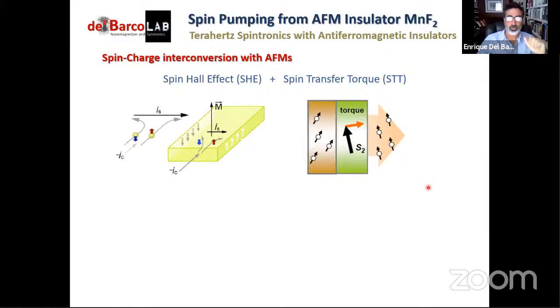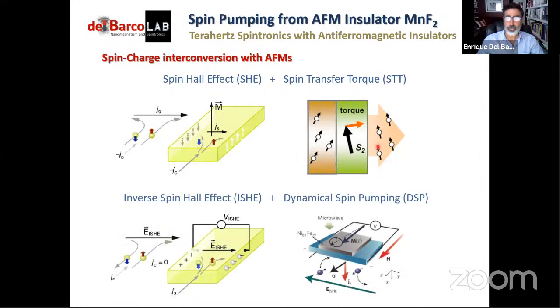All right, so I'm just portraying two of the most common tools that people in spintronics use to control the magnetic state of the system. It's the combination of the spin Hall effect, which converts charge current into spin current, and the spin transfer torque effect, which is basically that the spin current we inject in a magnetic material induces dynamics, right? That's one way of controlling the magnetization. But again, back to Newton's third law, we have the reciprocal effects of both of these effects that allow us to do exactly the same physics, right? The inverse spin Hall effect converts spin current into charge current, and the dynamical spin pumping converts magnetization dynamics into a DC spin current, right?